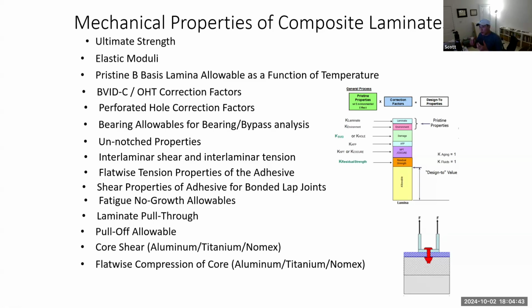Core shear. So the core is going to be seeing transverse shear in two directions, the ribbon and transverse directions. So there's an interaction that occurs between both directions. What is the capability of the core? And then flatwise compression of the core. So under a curved part, if there's a bending moment, it can actually impose a flatwise compression, crushing the core. And so we've got to check for that too.